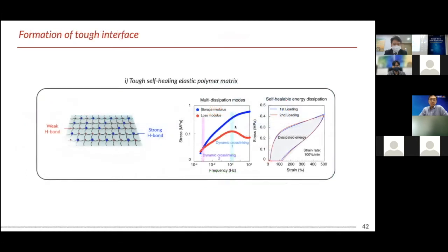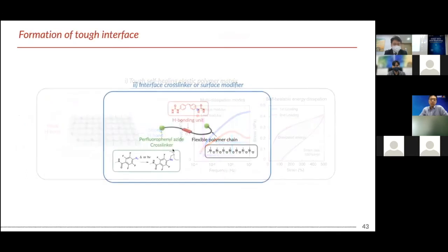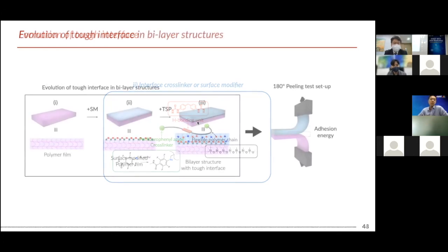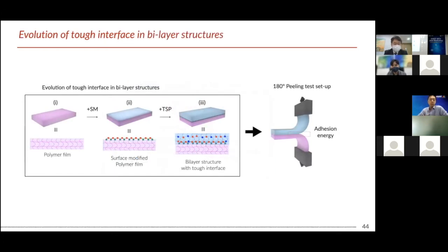So one is a self-healing polymer, and the other one is based on the perfluorophenyl azide cross-linker. So they have two cross-linkers to make the cross-linking between the two surfaces, and also they have the hydrogen bonding unit to promote the nice topological interaction with the self-healable polymer. So this is the basic principle of the evolution of the tough interface.